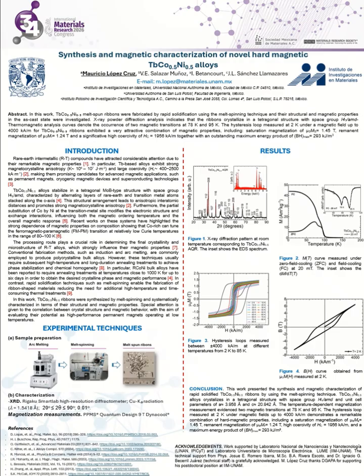Now I'm going to show how the ribbon alloys were obtained. First, the master alloy was fabricated by arc melting using the required stoichiometric amounts. It means elements with more than 99.9% of purity and under a high purity argon atmosphere. Then, these 3 grams of alloy were melted and remelted several times to ensure chemical homogeneity. Subsequently, melt spun ribbons were produced using a melt spinning system. That's how rapid solidified ribbon alloys were produced.